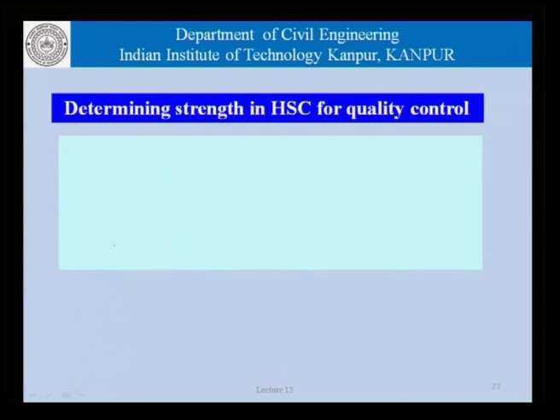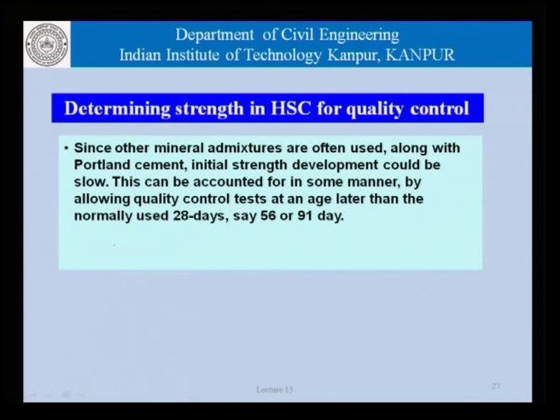Now, let us talk a little bit about determining the strength for high strength concretes as far as quality control is concerned. One thing that comes to mind is the age at which the quality control should be carried out. Since mineral admixtures are often used along with Portland cement, strength development, at least in the initial part, could be slow, and this could be accounted for in some manner by allowing quality control tests at an age later than the normal 28 days, say 56 or 91.